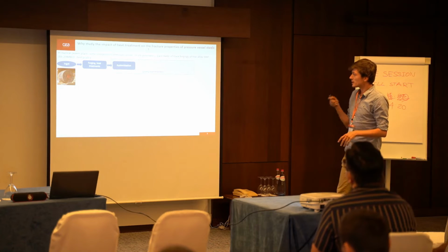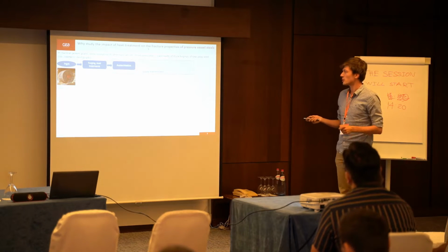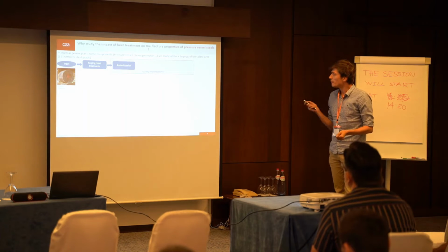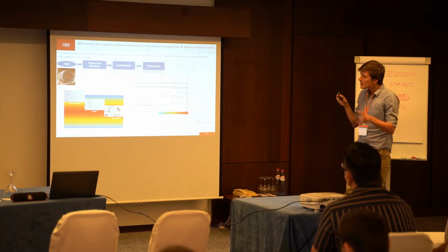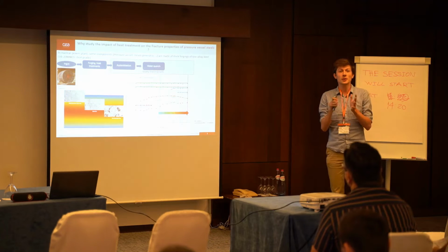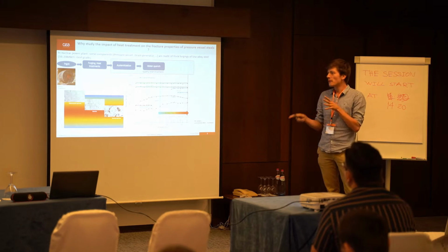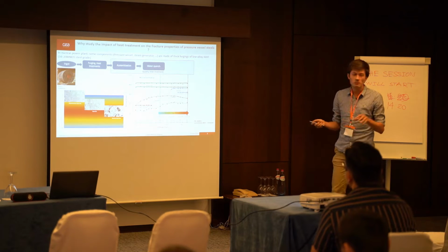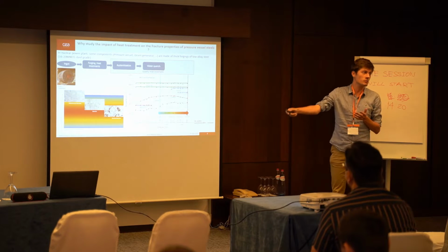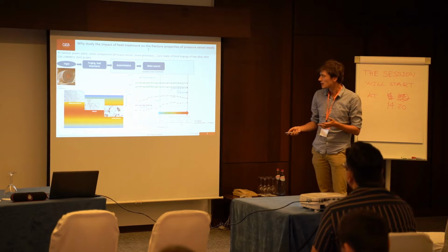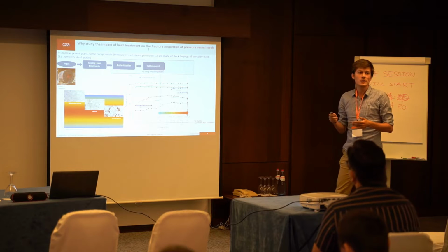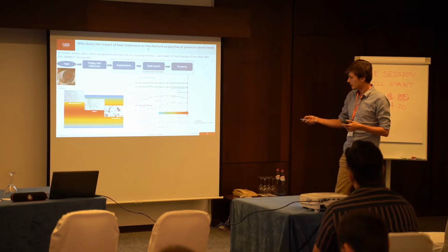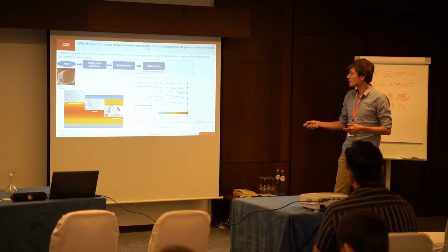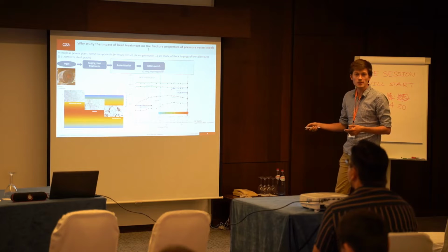Then, the quality heat treatments will aim at giving the material its required mechanical properties. It starts with an austenitisation at around 900 degrees during several hours, followed by water quench. During the water quench, since the components are very thick, the thickness usually ranges from 100 mm to 700 mm in the most extreme cases, there will be a gradient of cooling rate through the thickness.